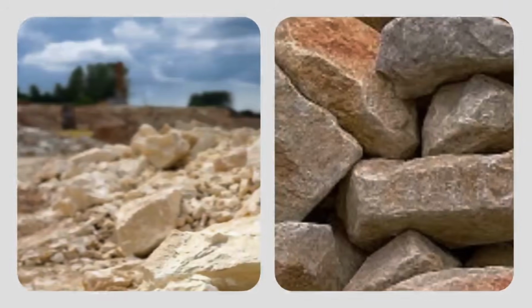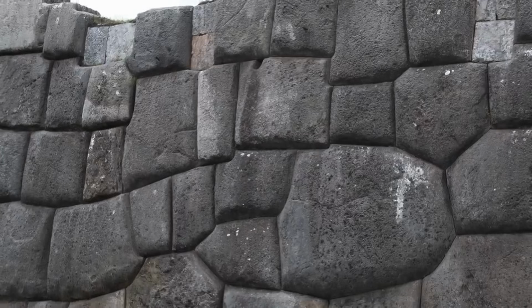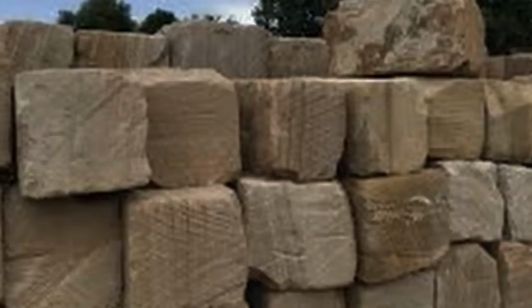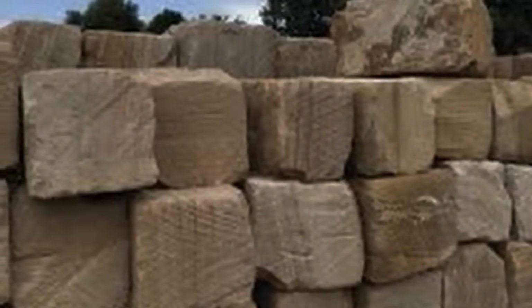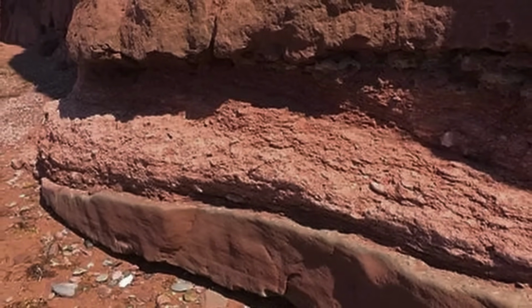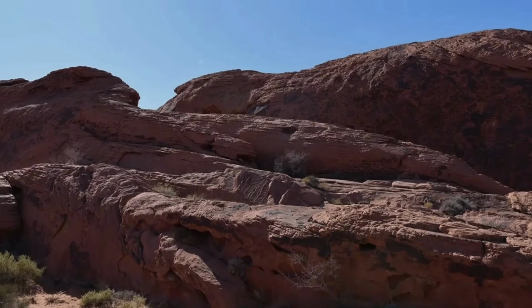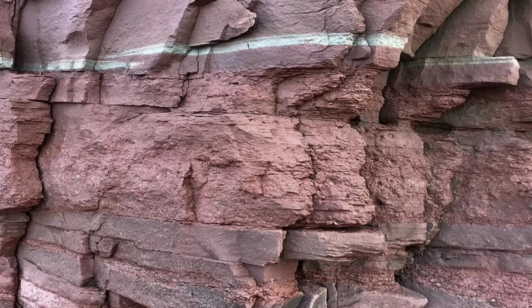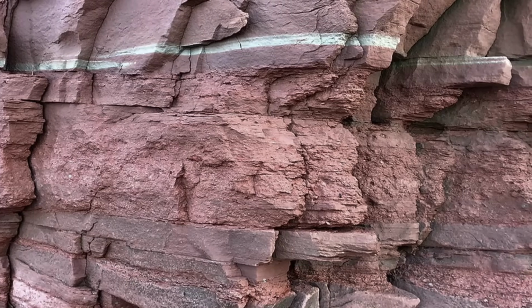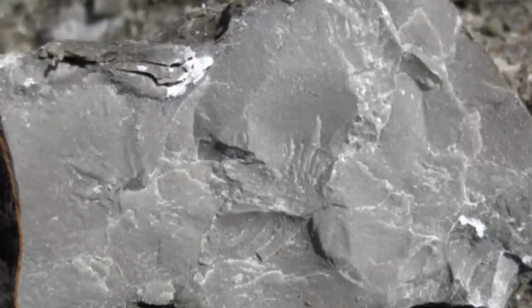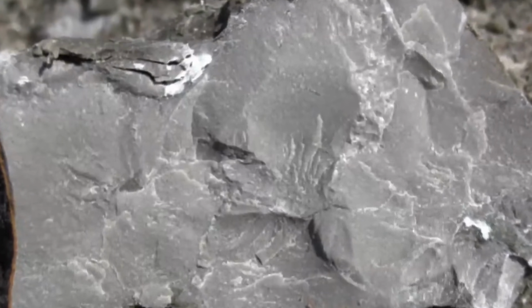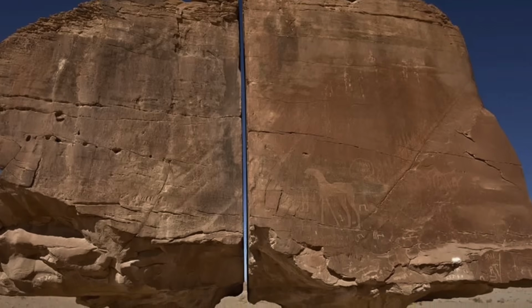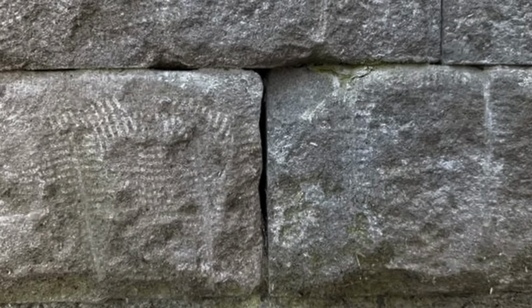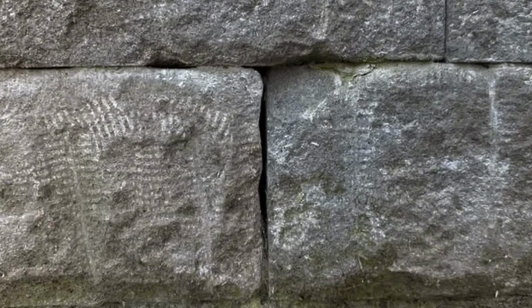Limestone and sandstone, the stones medieval Europe built almost everything from, were laid down in sedimentary layers over millions of years. Each layer is stronger along one axis than the other. If you place the block so the layers run horizontally, the weight above pushes straight down into the grain, and the stone holds. If you flip it, the weight now pushes along the grain. Water gets between the layers. It freezes. It expands. The stone splits along its own geological weakness. A perfect block of limestone, placed wrong, can shatter in a single winter.